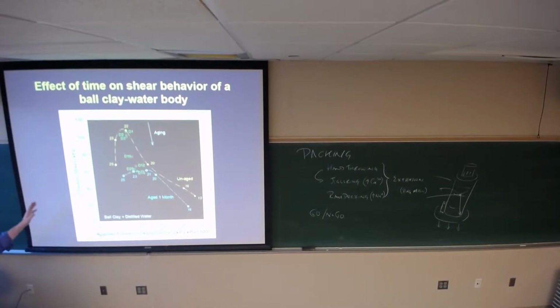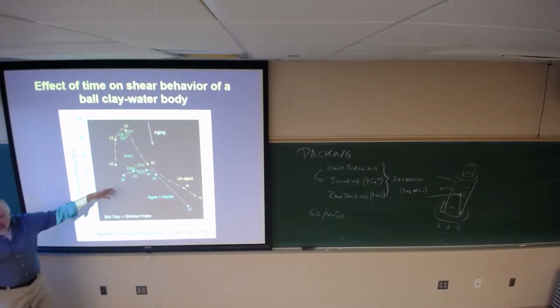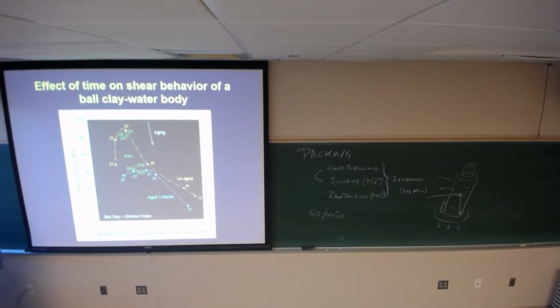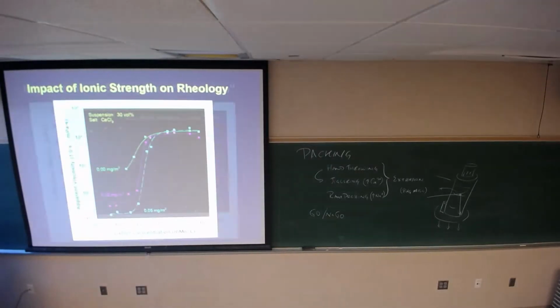Now, this is a month, right? But all we had was ball clay. If I bring in feldspar, then I get a lot more dissolution much more rapidly. Or if I pick a different clay, I get a lot more dissolution much more rapidly. So we're seeing the evidence for aging, okay? And let's see if we have anything else that's important. We have this.